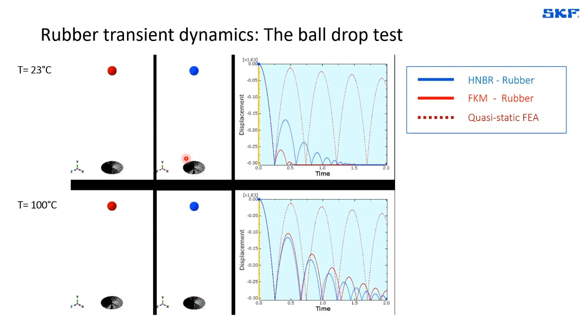Here, what we can see is basically the experiment on which I based the question on the previous slide. And I would like to just demonstrate what exactly happens. In fact, the two balls are hitting the floor at the same time. And we can see that the blue ball in this case, that has the lowest glass transition temperature, is bouncing the highest and bouncing the longest at ambient temperature. However, the misconception here is to believe that this is due to the glass transition temperature. In fact, it is not. It would be a mistake to base this on the glass transition temperature.